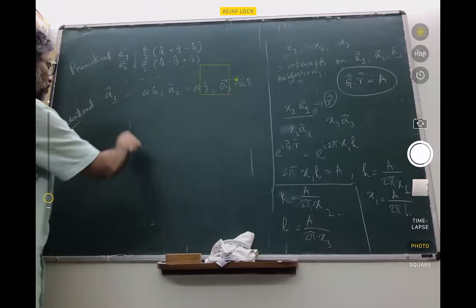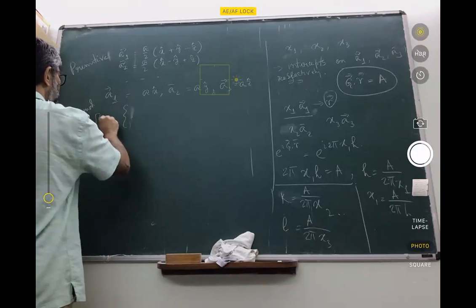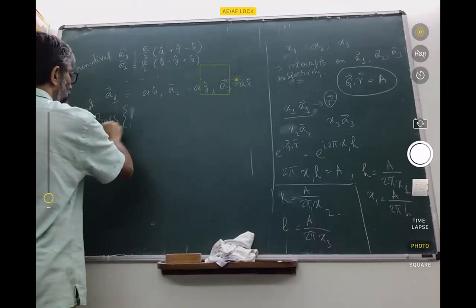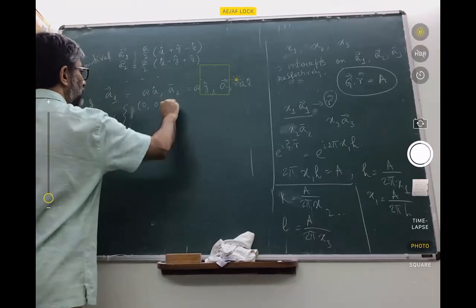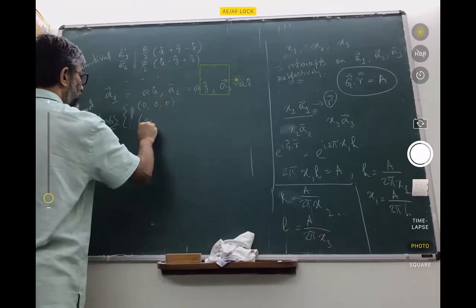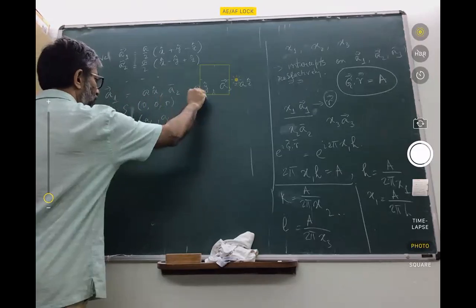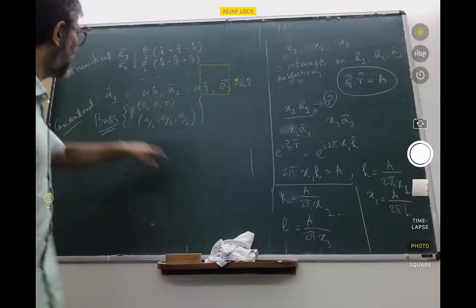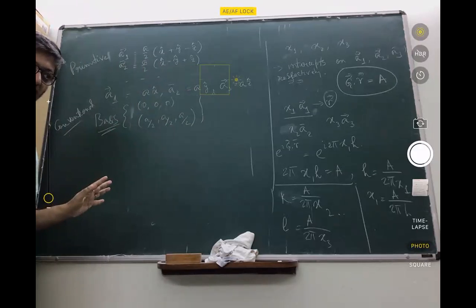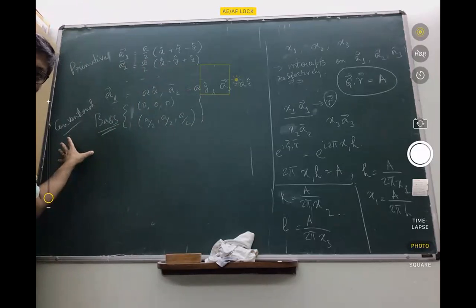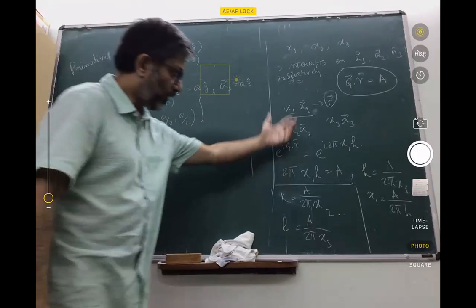So then I have to have a basis of two atoms, one at 0, 0, 0, the other at a/2, a/2, a/2. So if I use this two atom basis and these set of lattice vectors, then I can describe the BCC lattice. So this is my conventional unit cell. And that is quite often used while talking about these Miller indices.